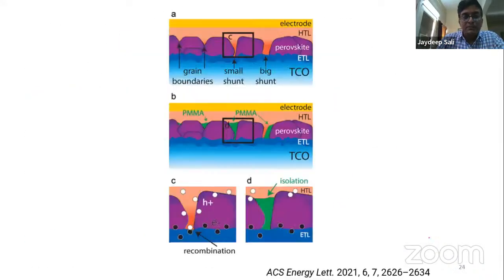Okay. So here you can see, whenever a perovskite thin film is formed, this is a cross-sectional representation taken from this publication. As you can see, this is a transparent conducting oxide, then electron transport layer, and on which a photoactive layer, that is perovskite, is formed. But when a perovskite thin film is formed by different methods, it is a common observation that it is made of different crystallites or different grains. So in cross section, you can see those grains in this way. It is clearly seen that in some grains, the grain boundaries may be compact, but somewhere you can have a small gap between the two grains, or you can have a large gap between the two grains.